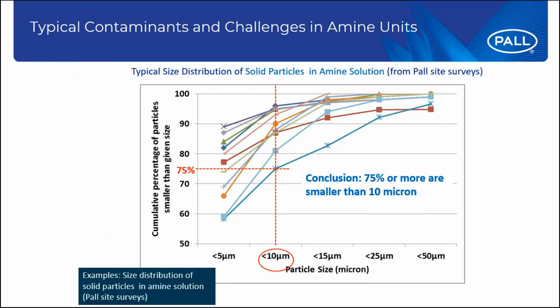From Scientific Laboratory Services, a division within Pall that does field measurements and testing and supports our customers, we have assembled our data from numerous sites where we measured solid contaminations. When we bring all these results into a graph, we see that 75% of those solid contaminations are smaller than 10 micron. It can be much higher. It can reach 95% that are very fine. So you can see the contamination can be numerous, but can also be very fine in its particle size distribution. Hence, you really need an improved technology to mitigate the contamination and to remove it sustainably.